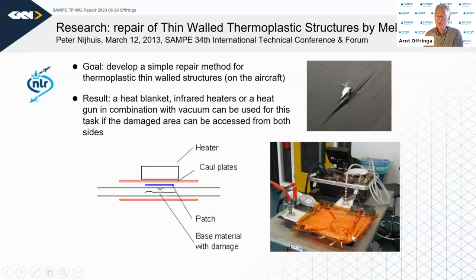On the picture here is a laboratory setup where you see a flat tool, and there's some bagging and there's a heating system. So in a laboratory, it's relatively easy to create a tool that will support your laminate, your product, and then you melt it and you fuse it together. The question is, how do you do that with a rudder or some other product in the field, when you're melting your polymer and you have to keep it in place?